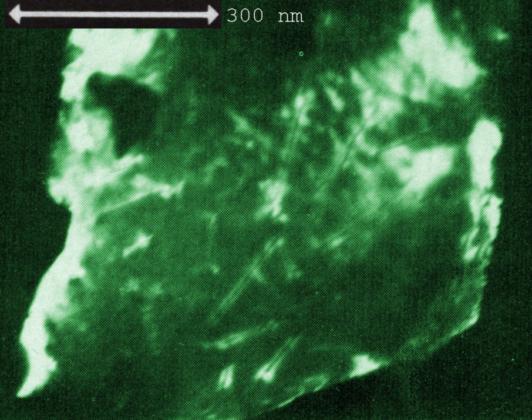Topic: Etching methods. Topic: Selective ion etching. Selective ion track etching is closely related to the selective etching of grain boundaries and crystal dislocations. The etch process must be sufficiently slow to discriminate between the irradiated and the pristine material.